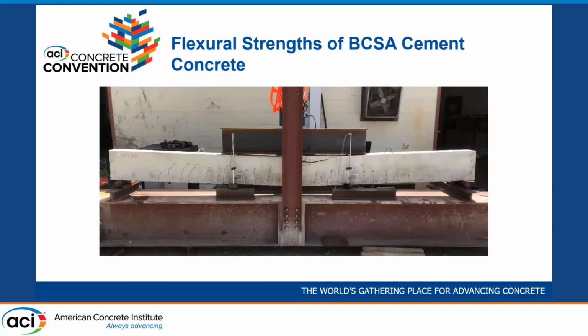This is what our beams looked like in the loading frame after they were tested. So they're simply supported. You can see the cracking pattern. You can see where the concrete crushed here in the middle. And you can see LVDTs that we use there to measure the deflection at the loading points.